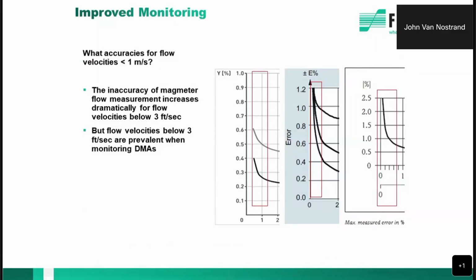So why below 3 feet per second? Like I said, that's the sweet spot for a mag. This is a particular calibration curve. So if you couple that with lead and copper, any injection of orthophosphates really exacerbates this. So this is from the flow rig what the calibration curve looks like. And again, you see about 0.3 feet per second. You can see that you're getting up to about 2.5% versus the 0.5% that they advertise.